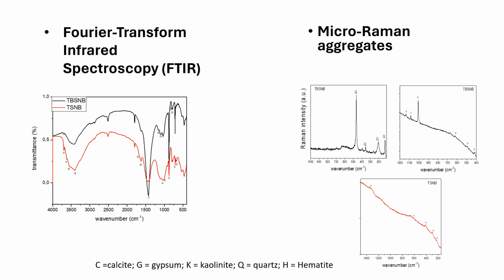In the TBSNB sample, the calcite is much higher than the other components, indicating the higher amount of lime as a binder, and the higher amount of calcite, characterized by a white color, is consistent with the lighter color of this sample, possibly due to the marine shells. With Raman spectroscopy, in the case of the TSNB sample, an iron oxide was identified. In the TBSNB sample, two types of aggregates were analyzed, one dark-colored and one light-colored. Quartz and gypsum were identified.